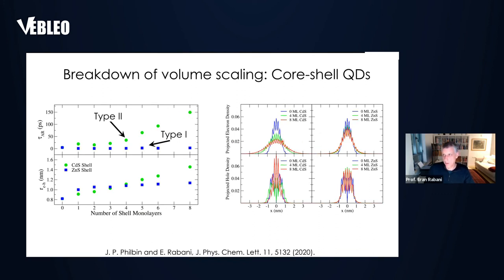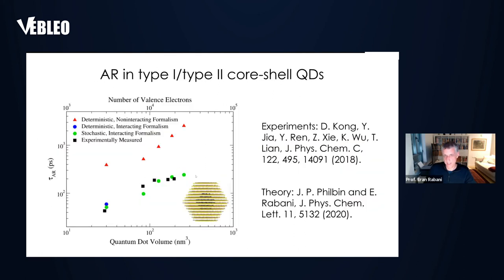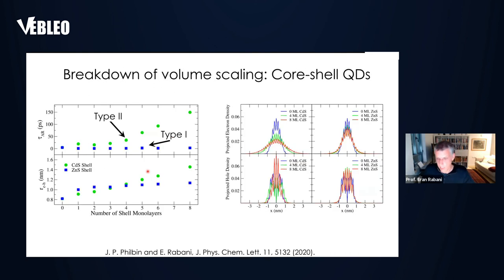On the right, I show projections of the electron density for cadmium sulfide and zinc sulfide shells — upper panel for the electron, lower panel for the hole. When you have a zinc sulfide shell, both hole and electron density are pretty much confined to the core region. Whereas in the type-two band alignment, the electron, being very light, can tunnel and reside in the shell quite dramatically, giving rise to the recovery of volume scaling. Not only can we recover results for core shells of relevant sizes, but we can predict how they would behave.